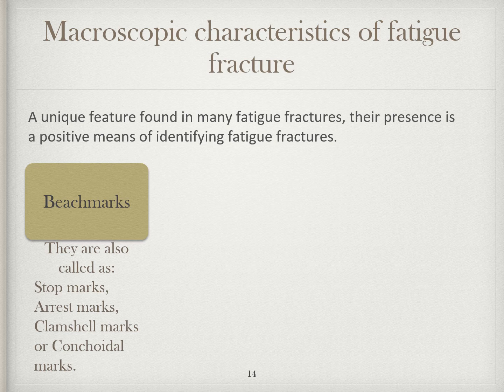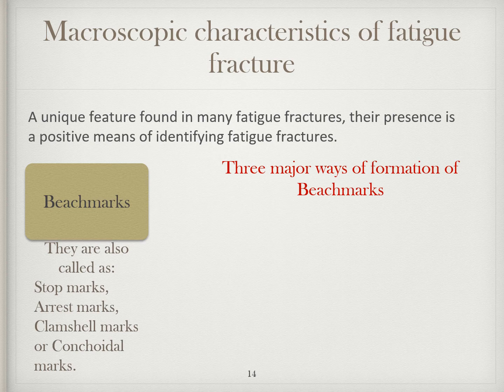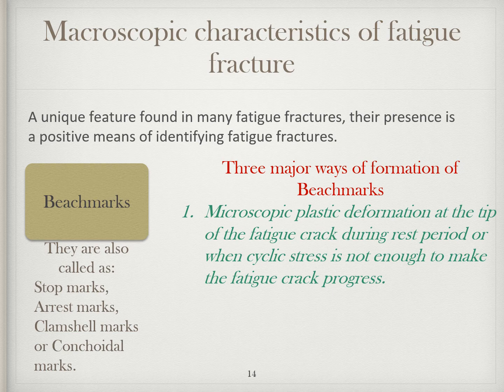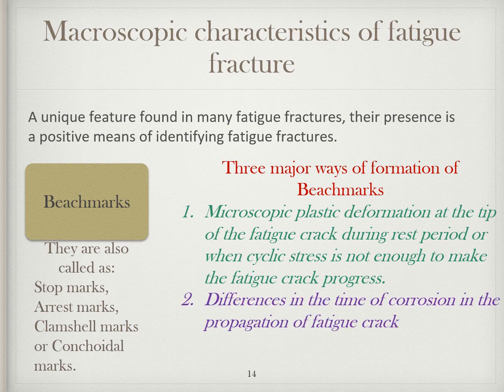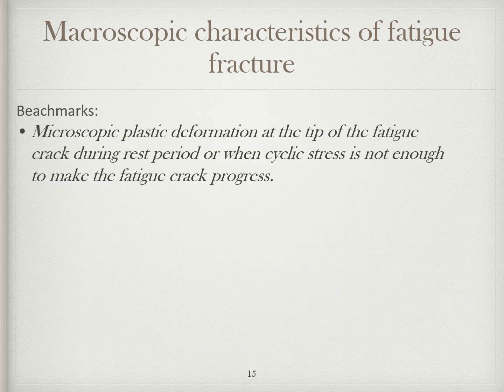Beach marks appear to be formed in three major ways. Number one, microscopic plastic deformation at the tip of the fatigue crack during rest period or when cyclic stress is not enough to make the fatigue crack progress. Number two, differences in the time of corrosion in the propagation of fatigue crack, and number three, large changes in the magnitude of loading frequency. Friends, let us now try to understand how each of the three ways mentioned earlier give rise to the beach marks.